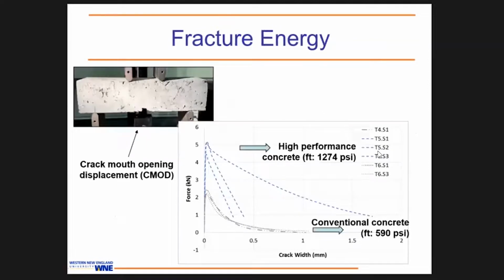After that, we tried to see the tensile performance by doing the fracture energy test. We have the beams, with a notch in the bottom, and a CMOD, crack mouth opening displacement, gauge, to look at how much the crack width is propagating, or gets wider, while we are pushing down, applying forces. As you can see in this bottom right corner, this is the force-crack width relationship, and a comparison between the high-performance concrete and conventional concrete. Both of them are without fibers. We can see the high-performance concrete has the higher fracture energy as well.